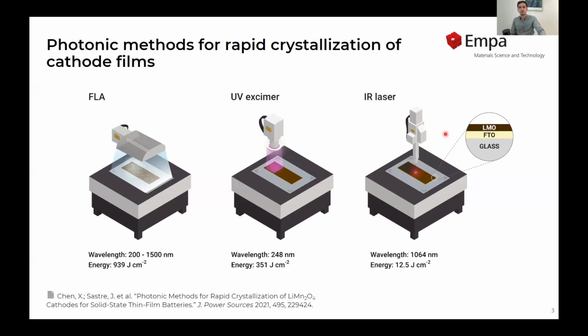And we tried to investigate these methods with a system consisting of a spinel lithium manganese oxide deposited by sol-gel method on FTO-coated glass.